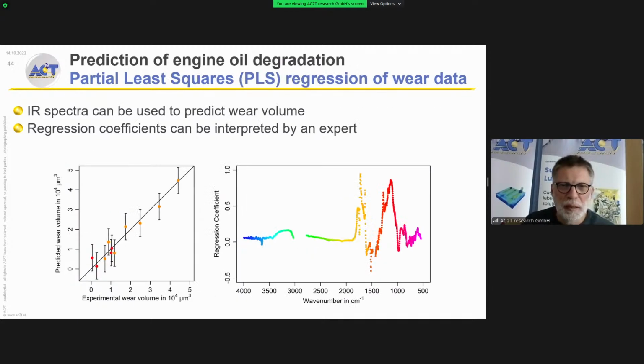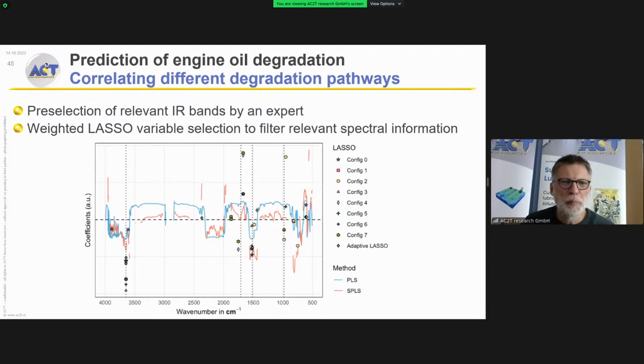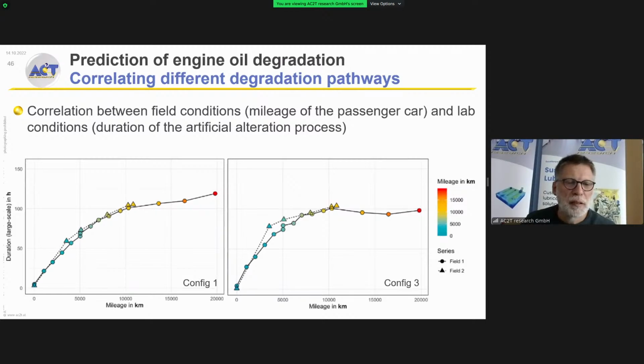What we also did is employ the partial least squares regression method to correlate our chemistry information with the wear and friction information which we got from the tribometers. Again, the interpretation is up to the expert, but the correlation is not so bad, I would say. And finally, we employed more modern statistical methods like lasso regression to correlate the mileage in the field to some duration in our reactor in the laboratory.